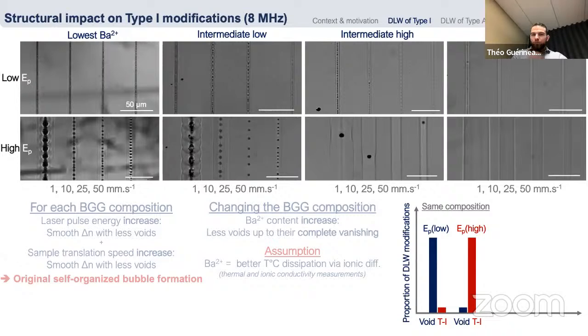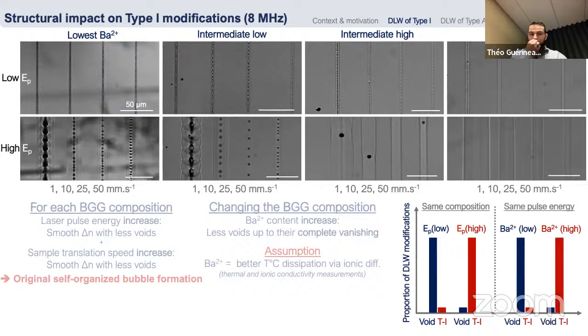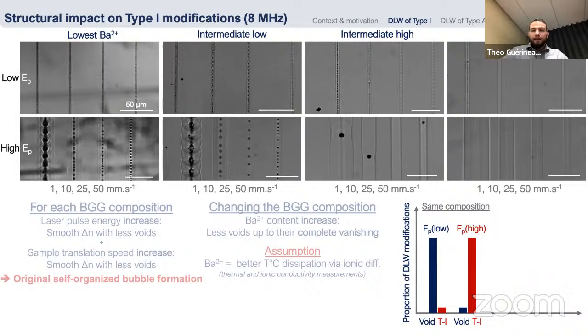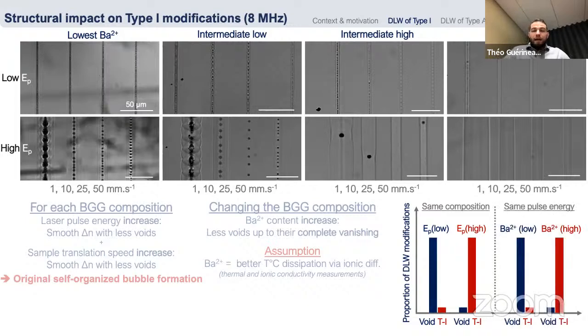Not to summarize, but just to see it from another point of view, here's some kind of representation of the proportion of direct laser writing modification as a reservoir for both of them, so either void or thermal type 1. For the same composition, at low pulse energy, we have the formation of a lot of bubbles. But when we increase the pulse energy, the concentration of bubbles is a lot decreased. And it's like we actually favor only the thermal type 1. And we observe actually the same thing when we fix the pulse energy but change the barium concentration.